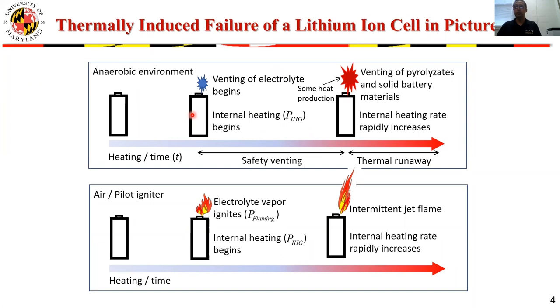If you repeat this same experiment in air and you ignite those ejecta, you will see a flame formed on the top of a single battery. As I point out, in the absence of any other devices, this flame is going to be blown off when the thermal runaway sets in, and then it will probably resettle somewhere at the very end of the thermal runaway, because the battery is super hot and can basically auto-ignite this flame once the ejection rate becomes sufficiently slow.